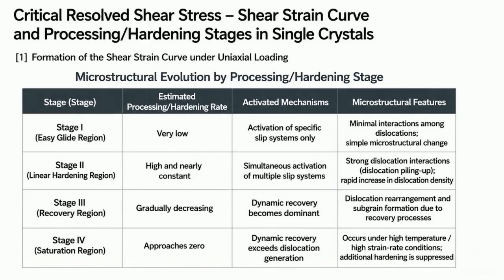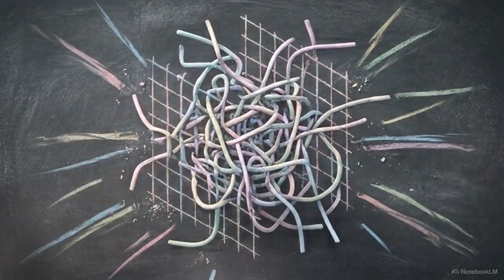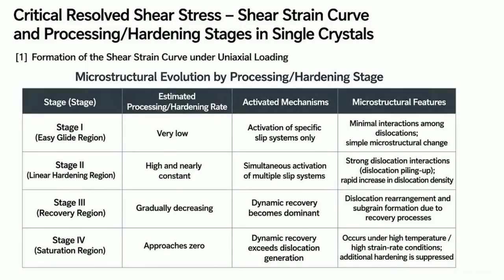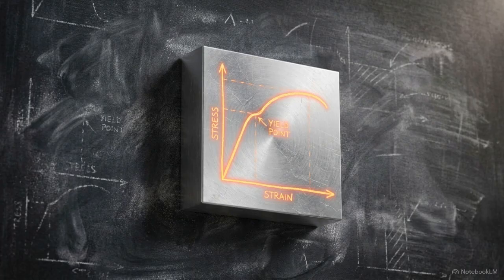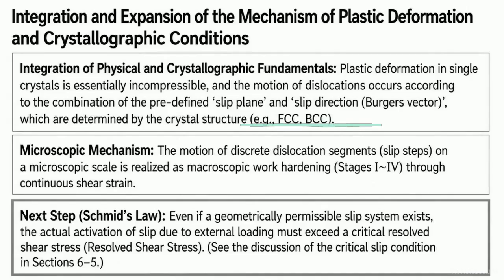In stage 1, the easy glide region, the hardening rate is low because dislocations move on parallel paths with minimal collisions. In stage 2, the hardening rate spikes as multiple slip systems activate, causing dislocations to pile up and block one another. This rapid accumulation creates a massive microscopic traffic jam that significantly increases the applied force required to continue deformation. Eventually, the curve flattens in the recovery regions as high stresses force dislocations to cross-slip or annihilate, relieving some of the internal pressure. The shape of this macro curve reveals the internal life of the crystal, from free movement to total gridlock. Macroscopic strain integrates discrete slip events, governed by the lattice geometry.